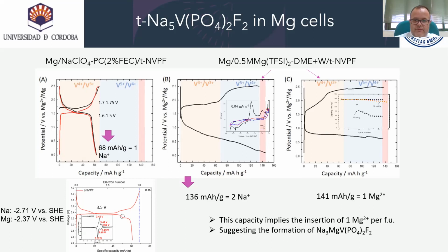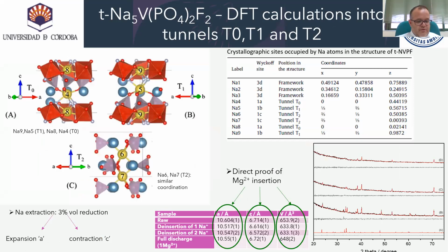The capacity retention of this magnesium cell is around 44% and 89% under 25 and 10 milliampere per gram over 25 cycles, respectively. Table 1 contains the atomic position occupied by all sodium atoms in the trigonal P3 structure, as well as their location in the structure. Having a look at the tunnel, the sites sodium 9 in T1 and sodium 8 in T0 are very similar. In the same way, the sites sodium 4 in T0 and sodium 5 in T1 are also very similar. Finally, the two sites in T2, sodium 6 and sodium 7, are also in similar coordination.